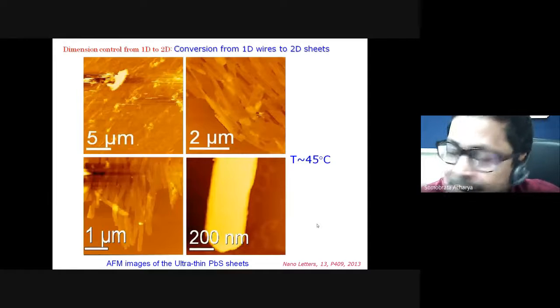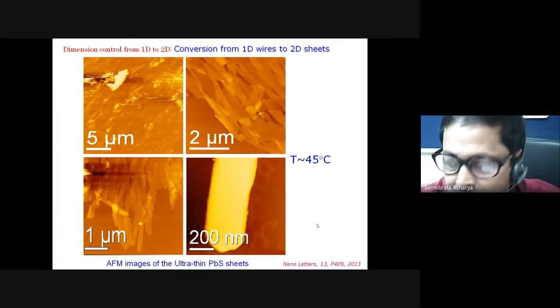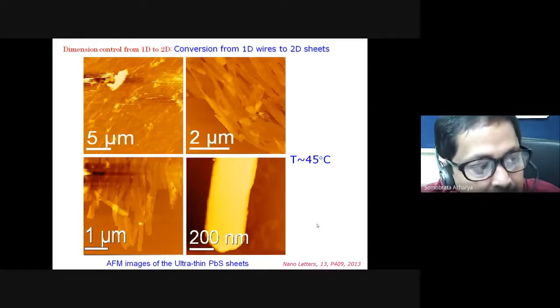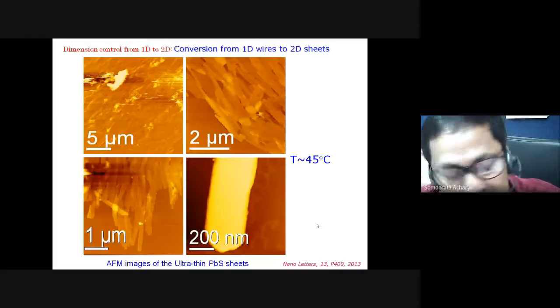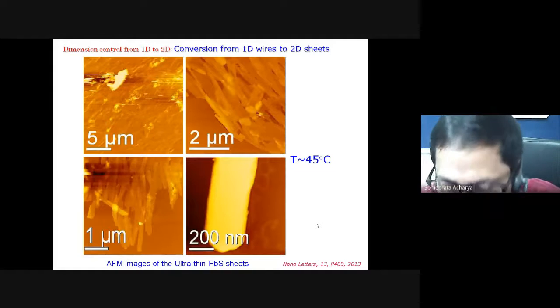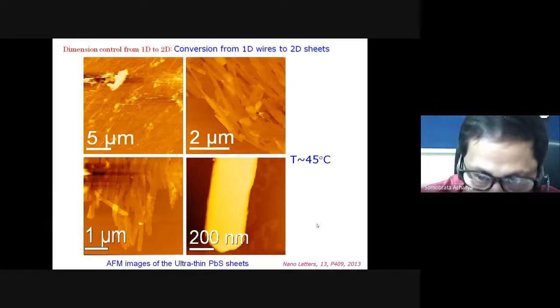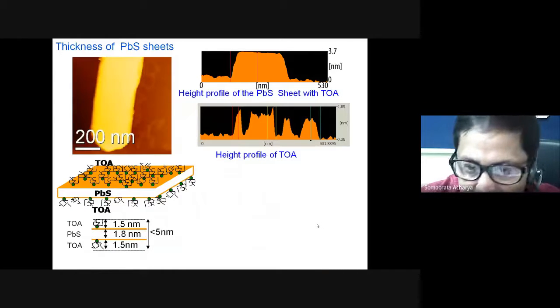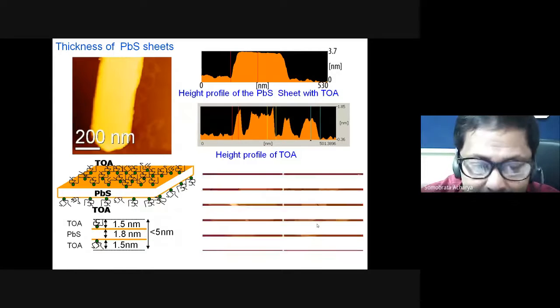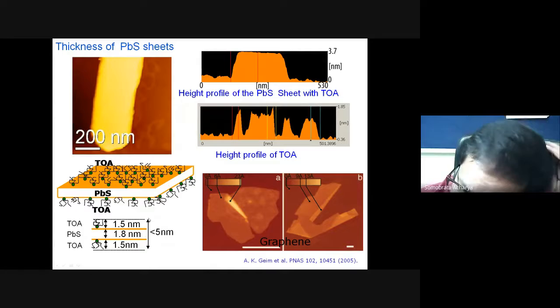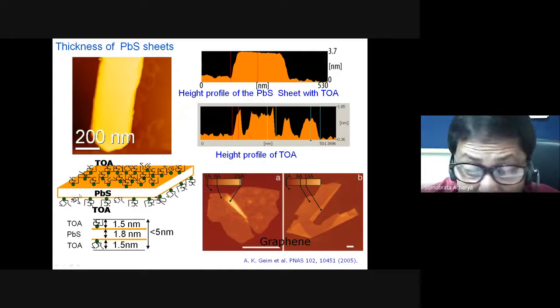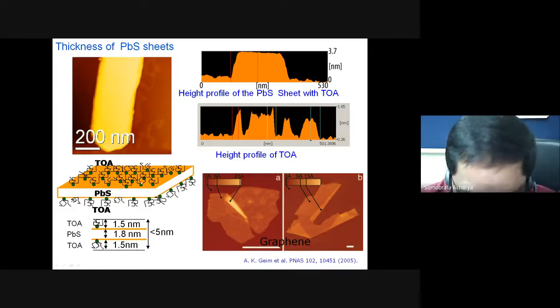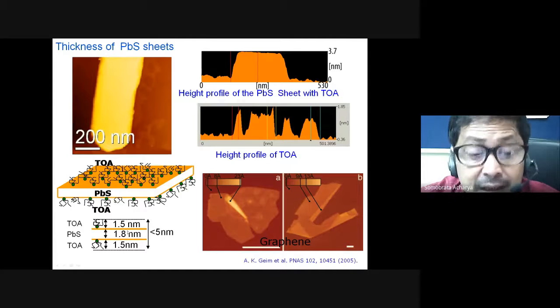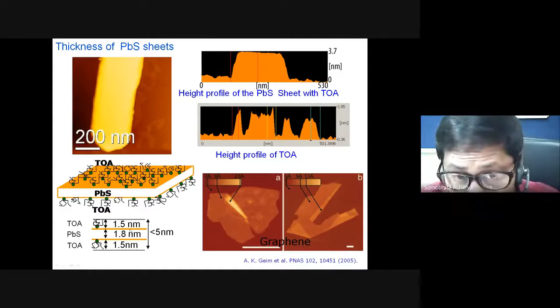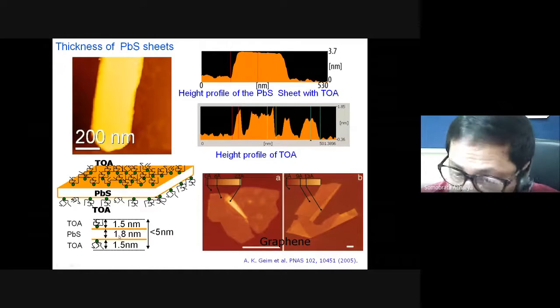That means you are doing nothing. You are just taking the nanowires or nanorods at the beginning, you are compressing it, and then you are heating it at a certain temperature to convert the shape of these nanocrystals. That means you are doing some kind of reaction at the air-water interface of a Langmuir trough. Okay. So then you can characterize the thickness of these two-dimensional sheets. For this case particularly, it is surfactant coated at the top and bottom surfaces of these two-dimensional sheets. So you just deduct the height of these surfactants from the top and bottom surfaces. So eventually you can get the thickness of your two-dimensional sheets, and that is to be around 2 nanometer here.